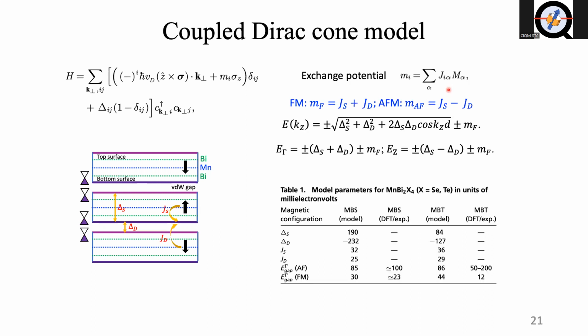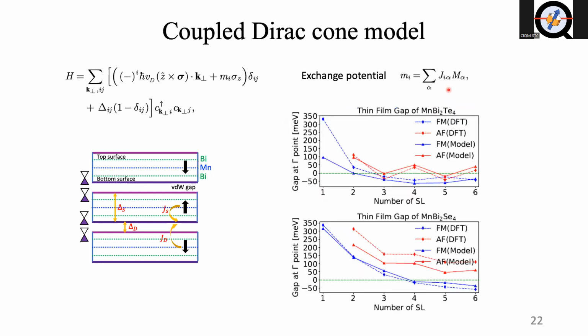So we use a very smart way to compare them with DFT calculation. There has been DFT calculation as well, or we can do our own DFT calculation. And then we can extrapolate those energies at those high symmetry points and compare them with our model. And then we can extrapolate those important parameters, delta S, delta D, the hopping term between Dirac cones, or the exchange coupling term between Dirac cones, and the magnetization, MF. And then let's take a look at the result first.